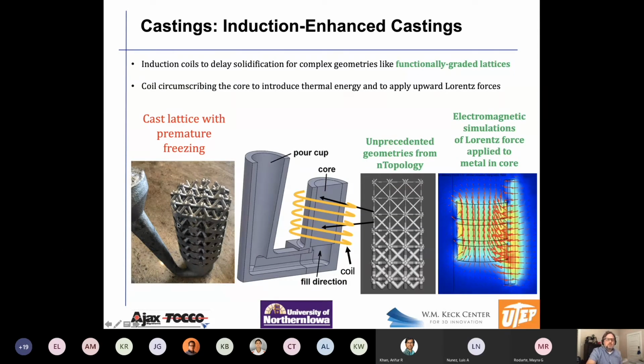So one of the things about 3D printing sand is you can do these lattices. The problem is if they're spatially varying like this, they're thick here and thin here, you pour the metal here and it comes down and fills in, and it'll prematurely freeze. These lattices have such high surface area that they freeze off early. This is like 2 inches shorter than it should be.